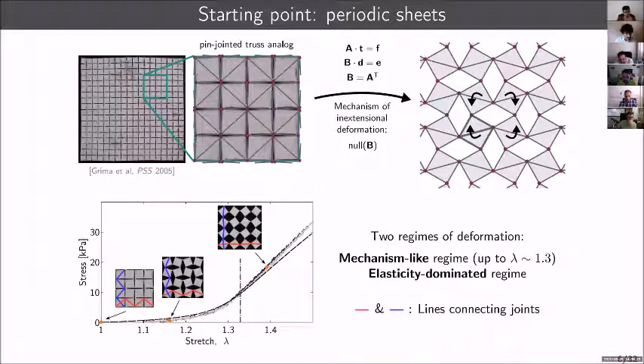Now, looking at these deformed images, we can see that in this low energy deformation region, the system behaves like a mechanism. You can see it because the tiles rotate just like they would in the kinematic analog. If you track these lines, the red lines are designed to connect the joints along the horizontal direction, and the blue lines connect the joints along the vertical direction. These lines are initially zigzag, but when you pull on the sheet, you make them more and more straight because the tiles rotate and align with each other. At one point, if you keep pulling, these lines are completely straightened out. If you keep pulling after that point, you excite the elasticity of the system rather than the kinematic mode. And that's why you have a second region that is much stiffer with respect to the first.